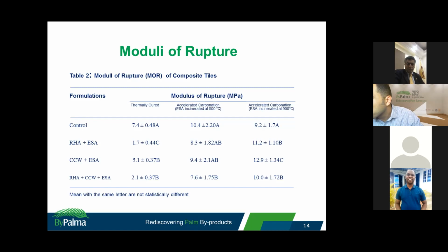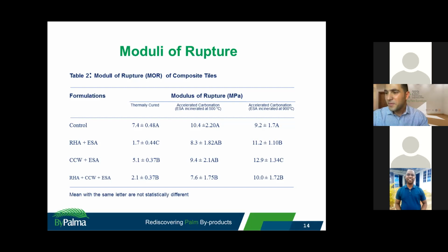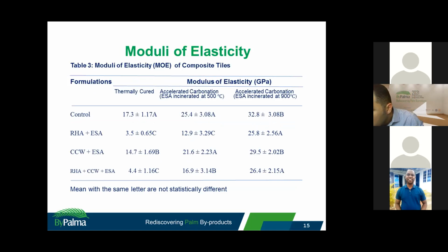If you check the one that we did not hydrolyze, we have 9.4. So it shows that the hydrolysis of our eggshell to calcium hydroxide gives us a good affinity for chemical reaction, which gives us a good performance for the composite. Then again, the modulus of elasticity of the material, it's tripled. It jumps from the previous presentation I had. Let's look, for example, at the one that was thermally cured, they are very low. But for the one incinerated at 500 degrees Celsius and the one incinerated at 900 degrees Celsius, you see the difference.